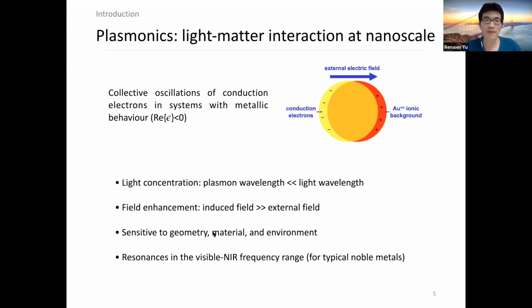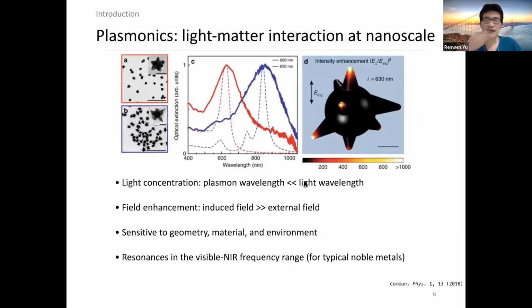For noble metal-based plasmonic systems, the resonances are typically in the visible to near-infrared frequency range. Here, I'm providing an example of plasmonic excitations. Basically here we have two gold nanostars with different shapes. From the far field optical spectroscopy, we can see two different peaks associated with these plasmonic excitations inside these two different nanostars. And at the resonance peak, when we look at the field distribution, we can see a three orders of magnitude enhancement of the field at the tip of the nanostars.